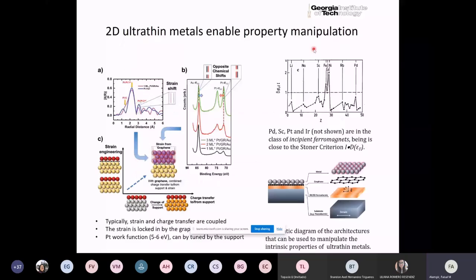Now, if you could make the support material be a two-dimensional material to begin with. So for example, graphene, if graphene was our support material, then we can imagine that you can tune the property of the catalyst that you grow by having a different metal or different material on the other side of graphene. From the other side of graphene, through charge transfer, you can influence the catalytic properties of your platinum, let's say, that you have on the other side of the graphene. So that's an electronic effect that you can control by choosing the right material below the graphene support.